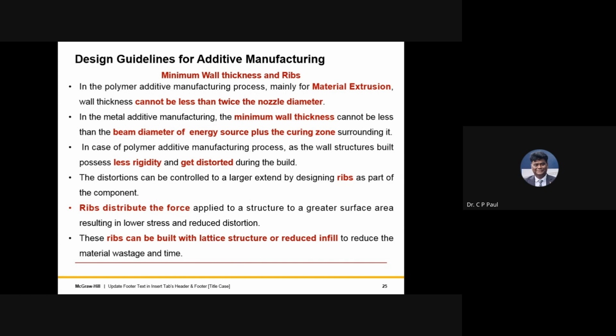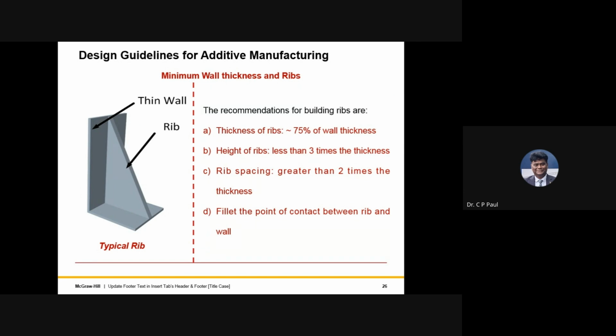Another thing that comes into the picture is how good the perpendicularity of the surface is, and there may be distortion or deviation while meeting the L-shaped structure and wall, which we want to be perpendicular. So people give some ribs, which distribute the forces while making the part, reduce the stresses and distortion, and reduce material wastage and time. If you have a thin wall, as I have shown you here, then people make a rib so that it can be built.